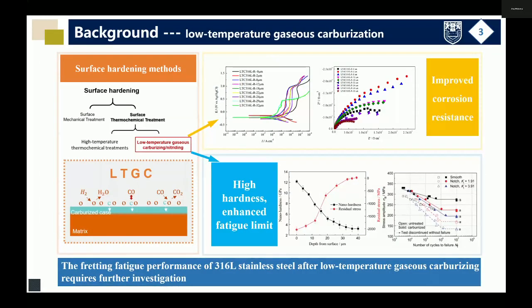Surface hardening techniques are usually divided into surface mechanical treatment and surface thermochemical treatment. However, surface mechanical treatments are difficult to apply to complex structures. High temperature thermochemical treatment can form carbides, which will decrease the corrosion resistance of stainless steel. So among these, low temperature gaseous carburizing can improve corrosion resistance, increase surface hardness, and enhance the fatigue limit of 316L. So, the fretting fatigue performance of 316L stainless steel after low temperature gaseous carburizing requires further investigation.